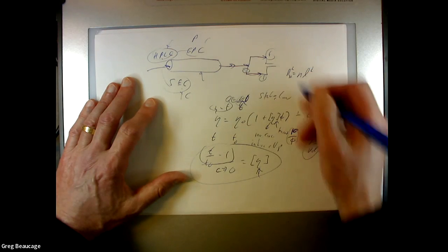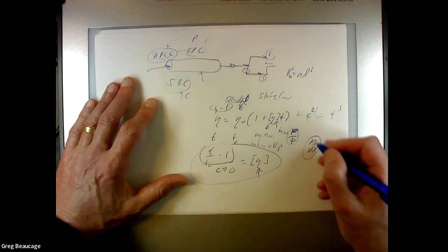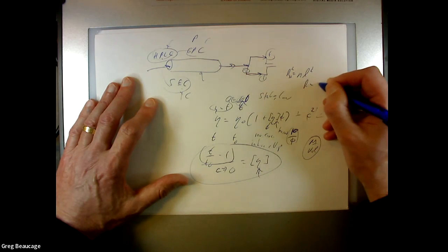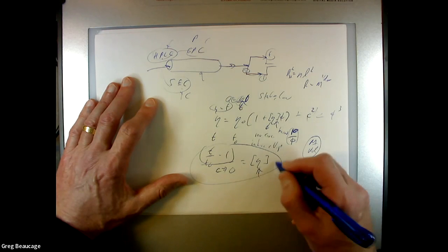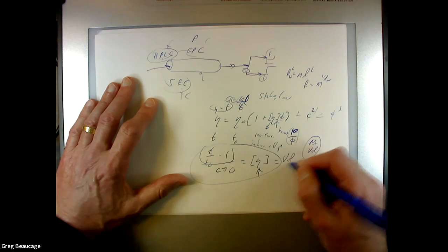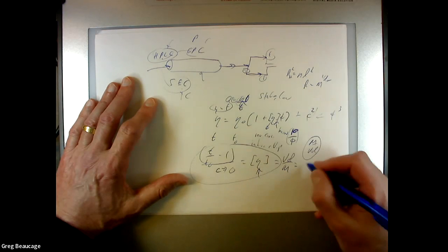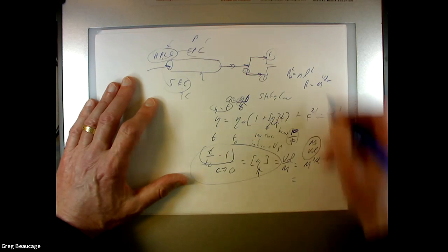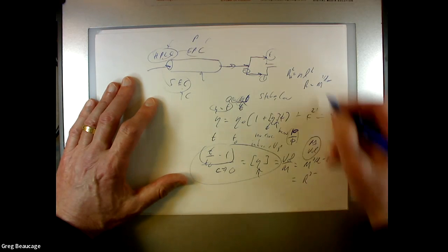Yeah, and then you just have RH here. So you have the volume of the thing, right? Basically this could be done in terms of the molecular weight. R goes with the molecular weight to the 1 by dF. So you could say that this thing is going to be volume for mass, right? If the volume is R cubed, then it's going to be mass to the 3 by dF minus 1. Or you could do it in terms of the R, so it would be R to the 3 minus dF.